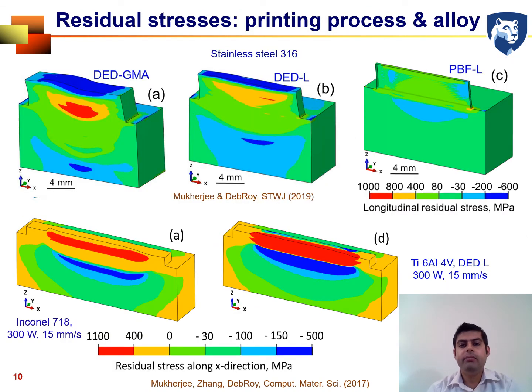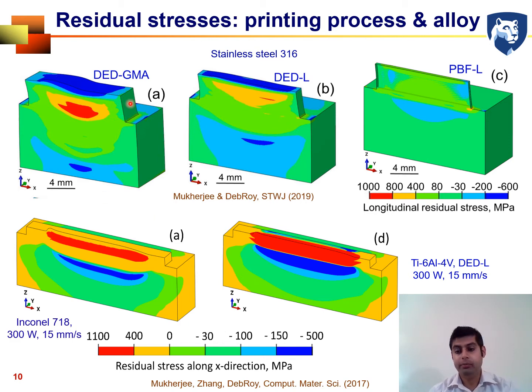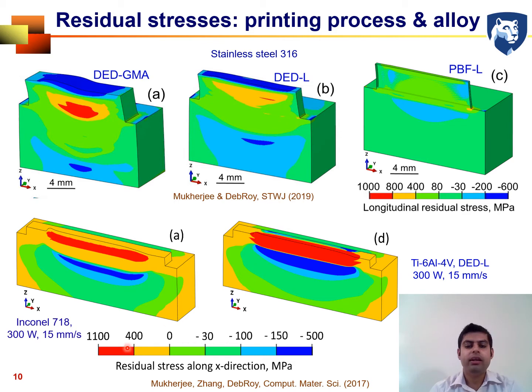This gives us the residual stress distribution for different printing processes and for different alloys within the same process. The difference in residual stress fields is very obvious: in arc-based DED (GMAW), since we deposit more material compared to powder bed fusion — where layers are often thinner than a human hair — the residual stress accumulation is much higher due to the cooling of large deposited mass. Similarly, titanium alloy accumulates higher residual stress than nickel alloy due to its higher yield strength.